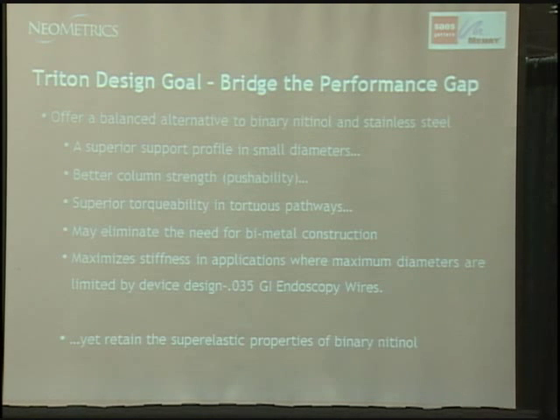What we're also finding is that there are certain applications like jacketed wires where an outer jacket is required for electrical insulation. The core material diameter is maximized because the jacket has to be a certain size and the OD of the product has to be a certain size. And this material allows an increase in stiffness, superelastic behavior, while maintaining the fixed diameter constraints that the engineer has to deal with.